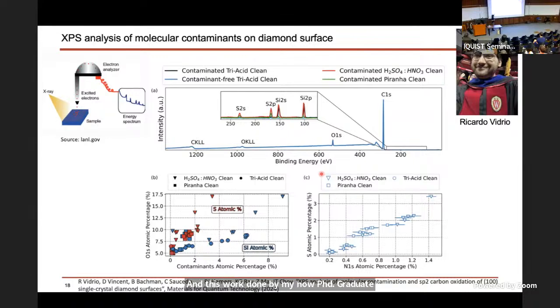So one of the things that we first did was try to understand why we see so much variation in the reported values of oxygen content in the literature. And what Ricardo found is that you have to pay attention to any surface contaminants in the diamond samples. What we show in the top plot is a survey plot showing the intensity of the photoelectrons as a function of the binding energy.